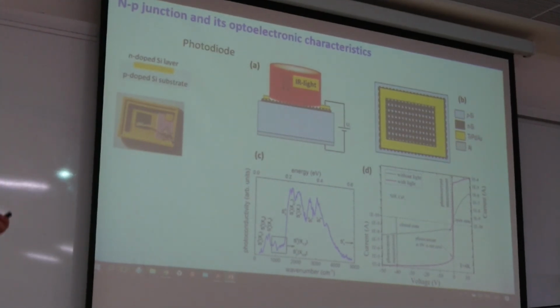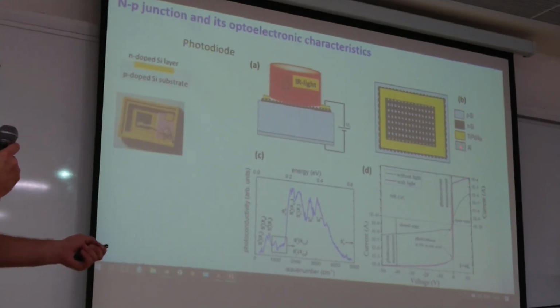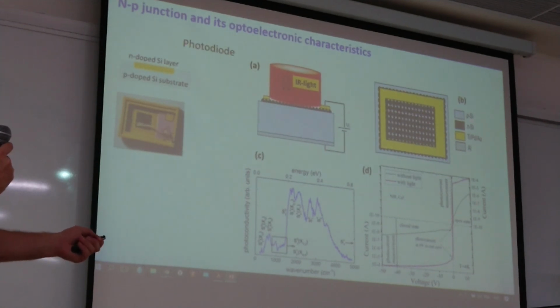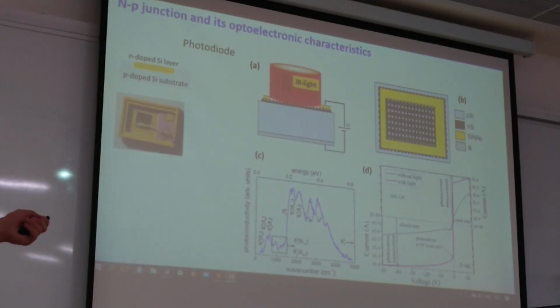So we have constructed a photodiode using an NP junction in very simple form. We used a p-doped silicon substrate, and we scanned a laser on its top to introduce sulfur. Sulfur is a donor impurity, an n-type impurity, so we have got an NP junction in this case. This is some kind of primitive device made just for scientific measurements. This is the top view of this system. We have a p-type silicon wafer, a square region of n-type silicon, and we have electrodes to make these measurements.